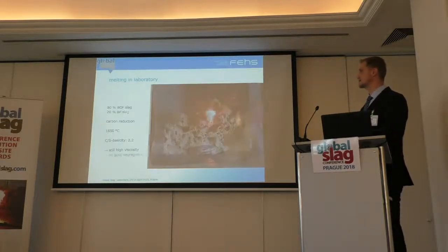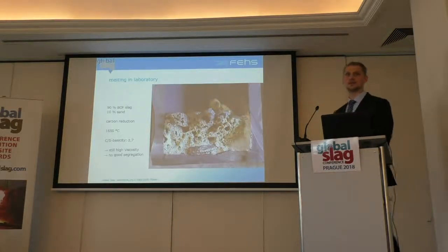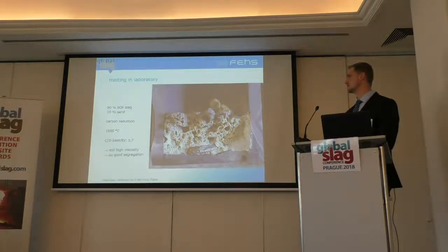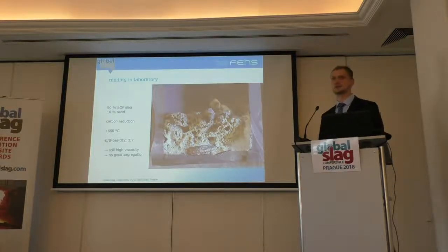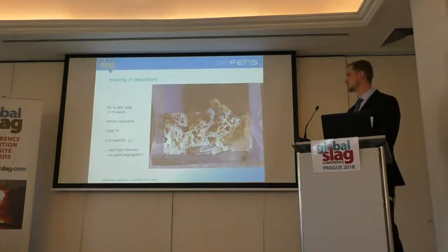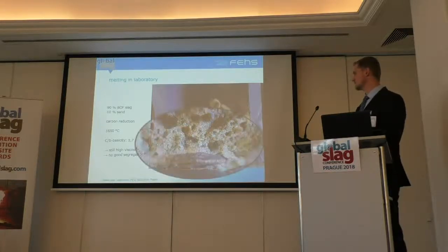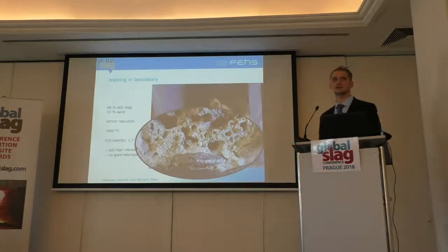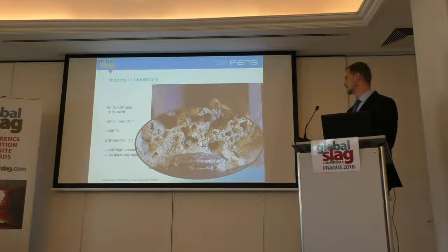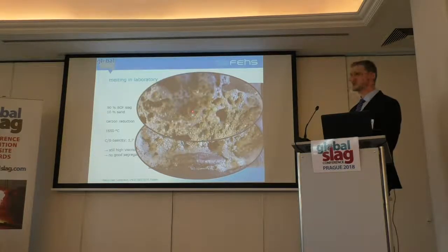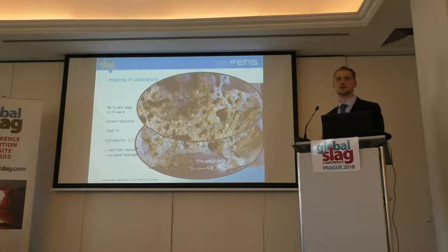So we made a third trial where we added 10% quartz, so nearly 100% SiO2. So we are able to decrease the basicity significantly to 1.7. Same temperature. We didn't pour the slag out of the crucible. We let it cool down in the crucible, and after this we cut the crucible to make this picture. We see here we got a segregation of the metal. At the bottom we got some metal, due to the high density it goes down and was collected there. But you can also see some metal pieces in the slag. So this means the slag still had a high viscosity.